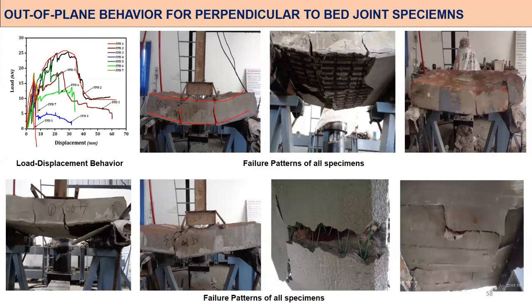Now this is FRP. There's a crack, and because the FRP modulus is higher than the brick modulus or geogrid modulus, exactly the support failed here. Whereas this is a geogrid, and this is again a geogrid. You can see here, in both cases, the mortar delaminates and the geogrid holds the force perfectly, because with geogrid we have 10 to 15% strain, which is very difficult to yield. Even in the tension machine, we were not able to make it yield.